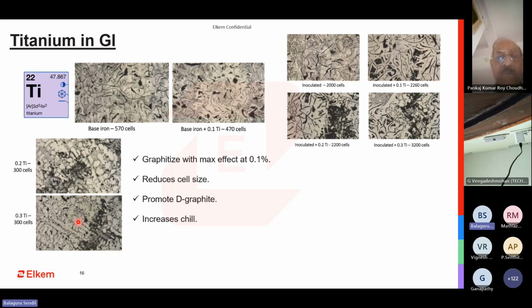When you are going to go for ductile iron, what it does, I'm sorry, in gray iron itself, this is the base condition. When I add inoculant to it, this is the base and this is directly post inoculant. This is 0.1 and this is what I'm going to do with inoculant. Of course, I can improve it with good inoculant, but if the percentage keeps increasing, my inoculant is also going to struggle. At 0.3 titanium, I'm going to see a bit of struggle. So it does a bit of refinement to your matrix.